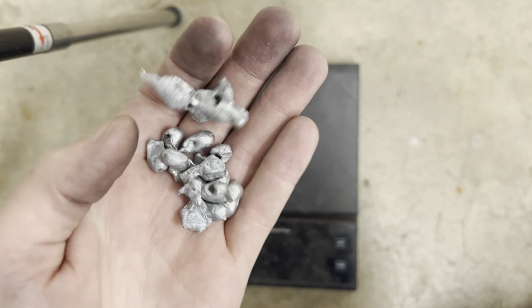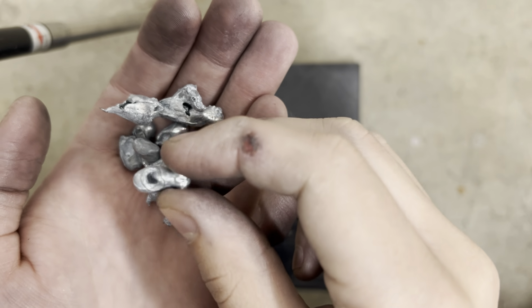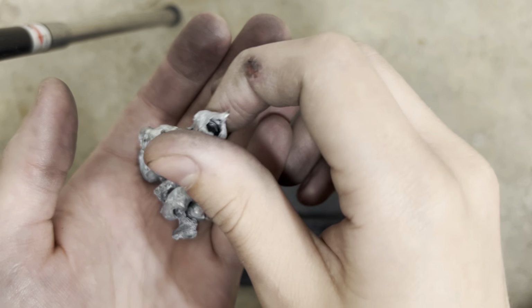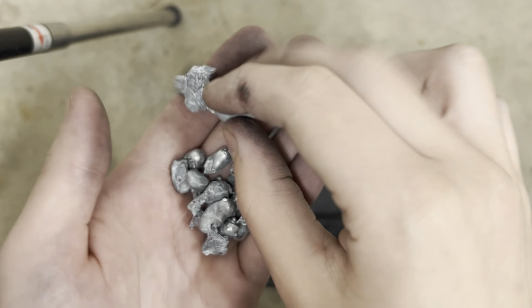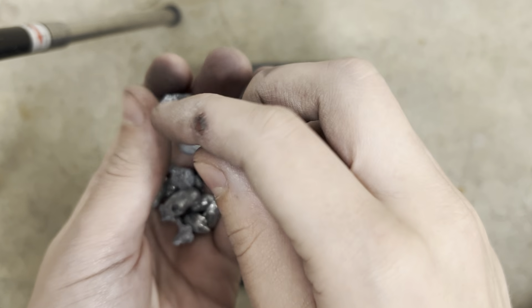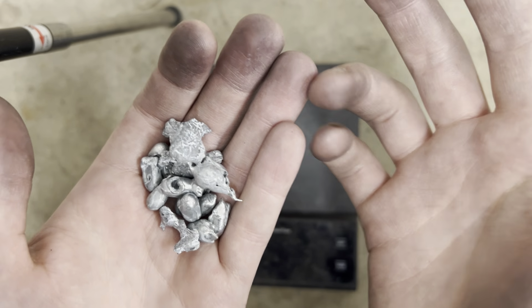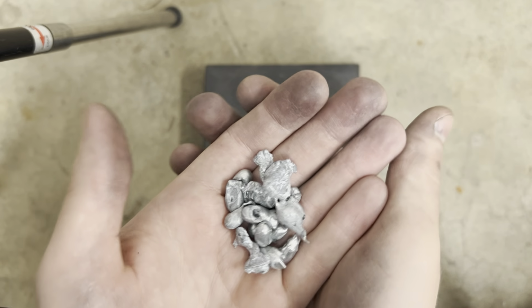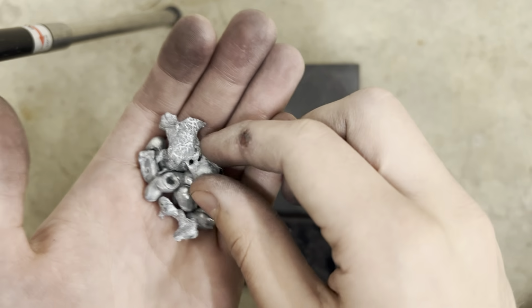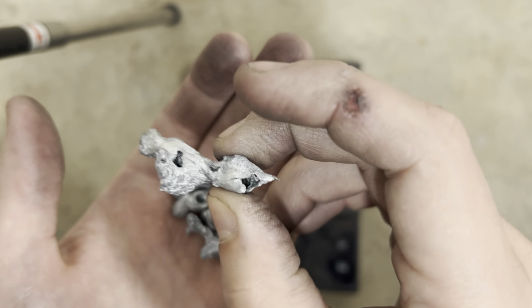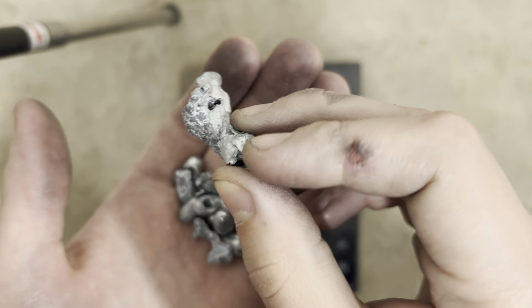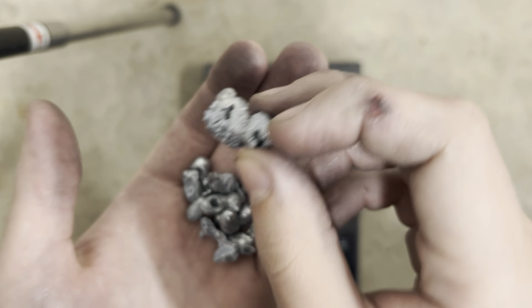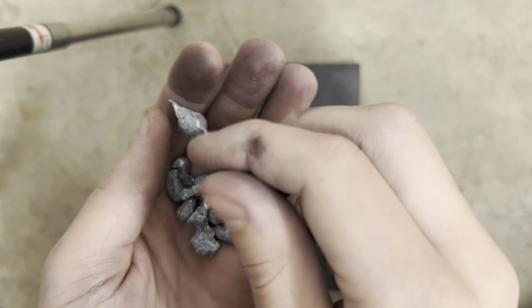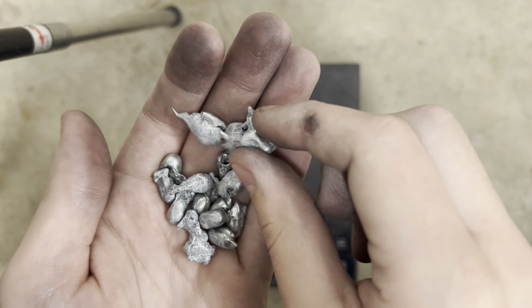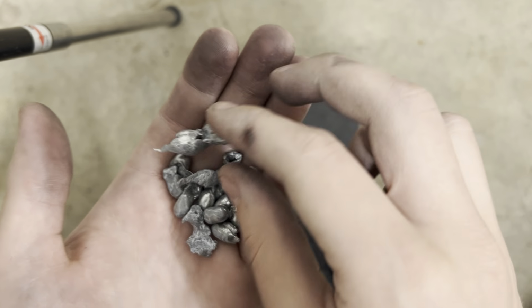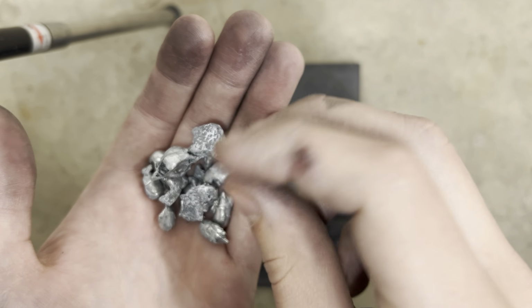And here is why it's important to turn your zinc into these little granules before casting. If you were to take all of this and add it in the form of a single ingot, that single ingot, when added to the molten copper, there's a good chance that because it's one big ingot and it's cold, it will begin to actually freeze some of that molten copper. And as we mentioned before, zinc boils at 900 degrees Celsius. So even when the copper freezes up when adding a large chunk of zinc, it's still very likely over that 900 degrees Celsius mark. So a bit of an unfortunate reaction happens.